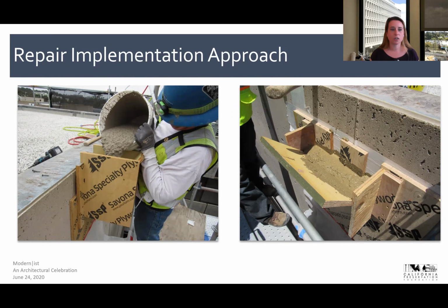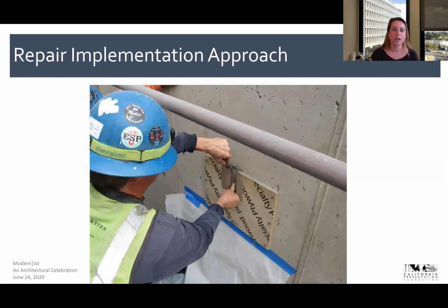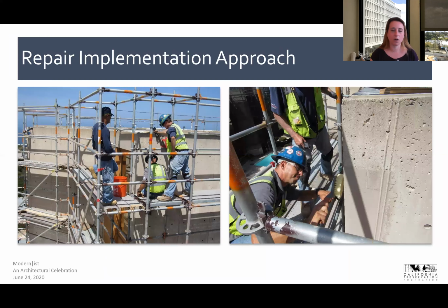And so the contractor really had a good handle on the material itself, the consistency to expect, and how long it would take to set up to be able to do some of the final finishing at that bird's mouth. This area had to be treated and finished really to hide it. We needed to reduce the visibility of how the concrete got in there for the overall approach for the repairs. And then, of course, the formwork would come off and the technical solution of tapping the surface with a nylon bristle brush was completed to achieve our bug holes.